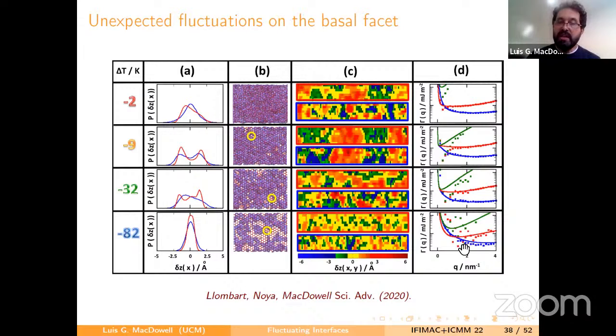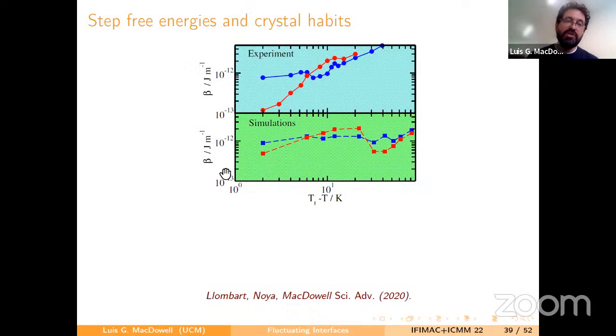And also we can map the fluctuations to our model. And when we do this mapping, then we get the parameters of the interface. And this allows us to measure the step free energies. What's the step free energy? It's the free energy that tells us what is the cost of growing the ice crystal. And so we have results here for the basal and the prism phase.